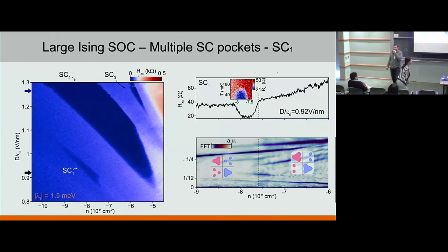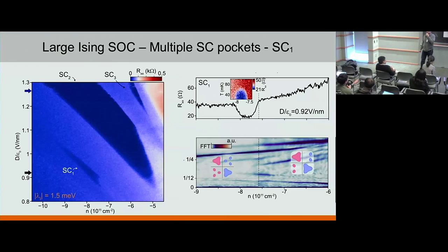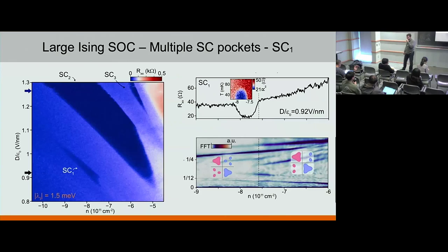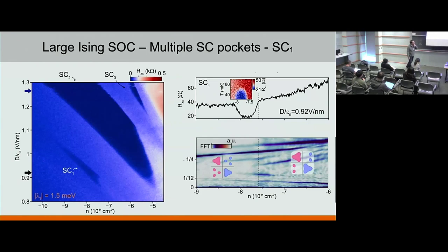You mentioned if you move to the sample with larger spin-orbit coupling, you actually need larger displacement field to stabilize the superconductivity. Is it counterintuitive? Do you have a reason why that's the case? I don't have a super intuitive reason why this happens. Some of our theory collaborators think that they have a theory that explains it, but it's still not super intuitive.